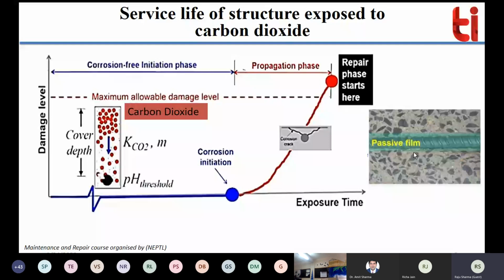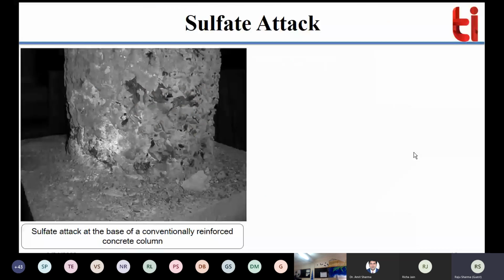Now this is the image, right? Just by seeing the image, it is very difficult to understand what happens. It shows that the concrete paste is completely removed, eroded, degraded, and some kind of appearance has come up on the surface, and this is not a pleasant look for the structure. You can see lots of aggregates. It means that the cement paste is completely degraded and removed from there, and it happens because of the sulfate,